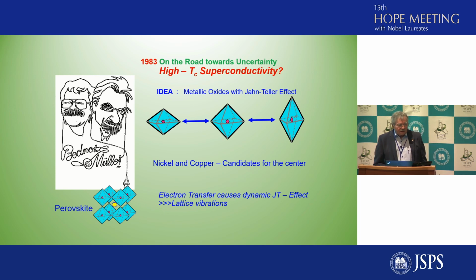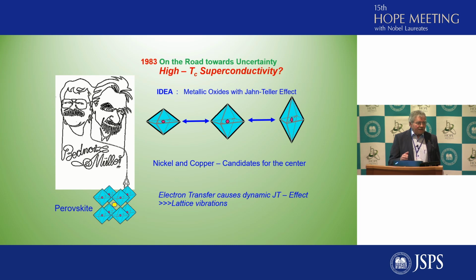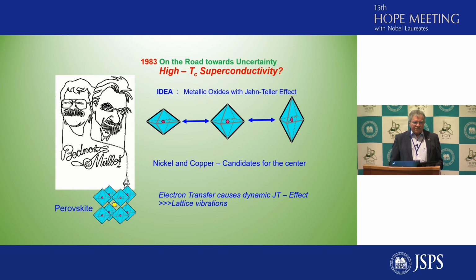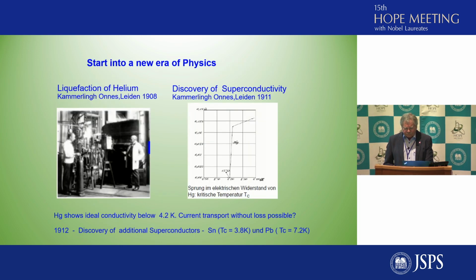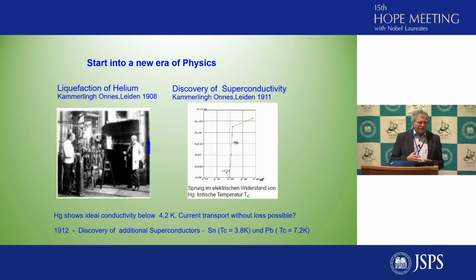And polarons or lattice vibrations were considered and are still considered as a driving mechanism for the intermetallic superconductors. That was along the BCS theory. So we thought when we would introduce nickel and copper as candidates for such a center in a metallic oxide, we could eventually observe superconductivity. So we embarked on the road towards uncertainty because we didn't have any hint whether this would be realizable or not.